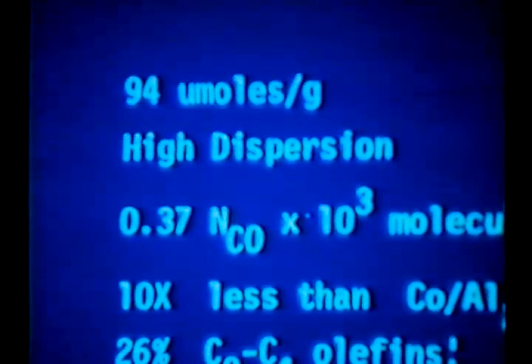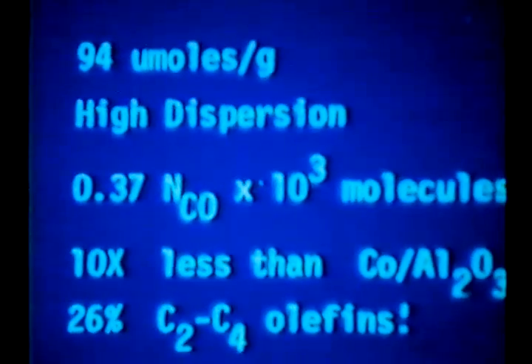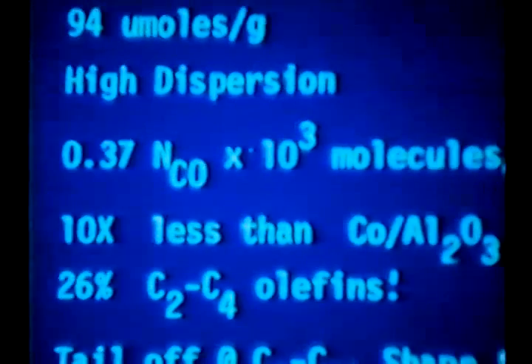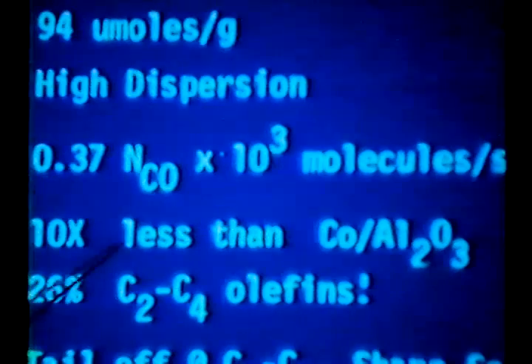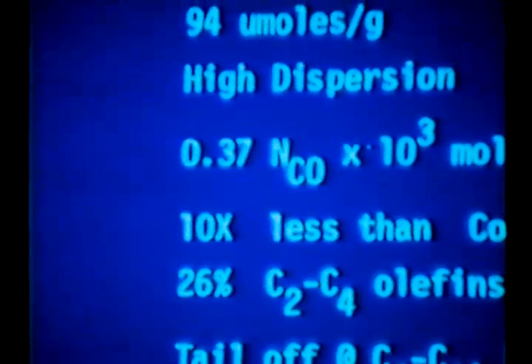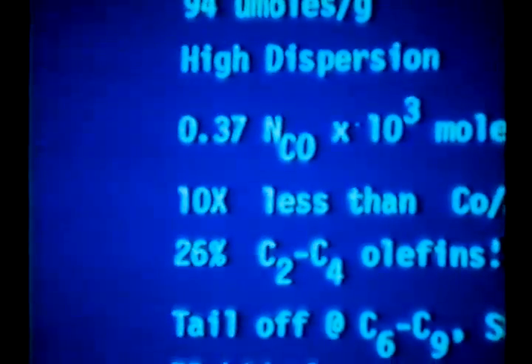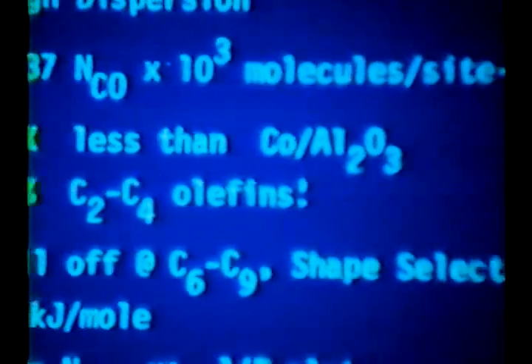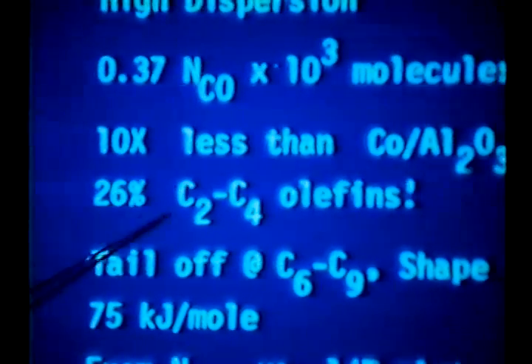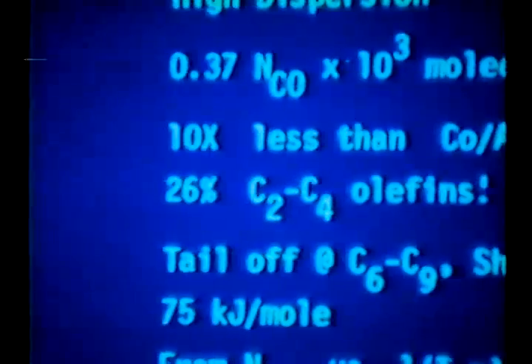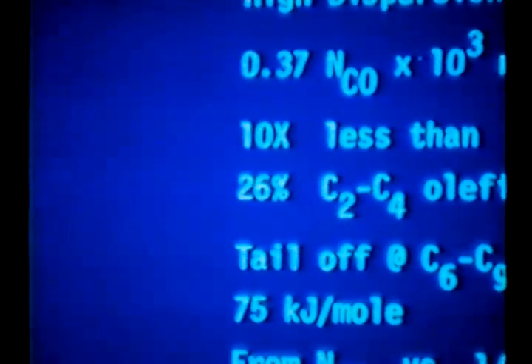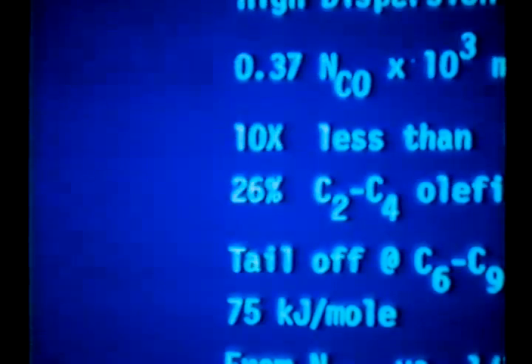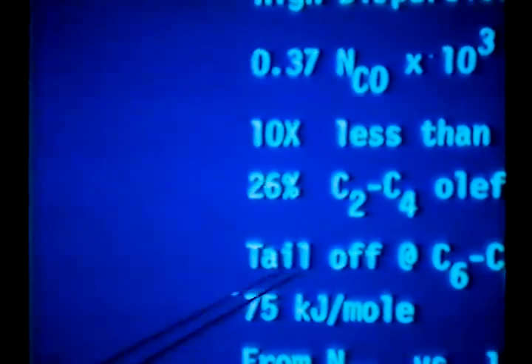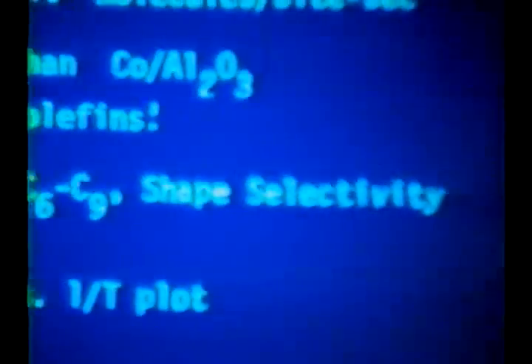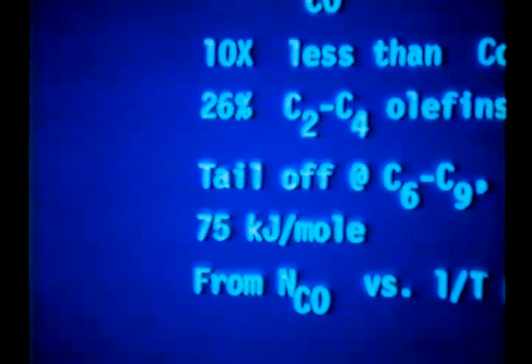That's what this data had to say. That's the good news. The bad news is this. The turnover frequency is extremely low. It's like 10 times smaller than cobalt on aluminum. Not very active materials. Real small, not very active. Very selective though, 26 weight percent C2 to C4 olefins. That's unusual for a cobalt zeolite catalyst of this type, with real small particles. There seems to be a tail off around C9, which may indicate shape selectivity. We're not exactly sure of that.